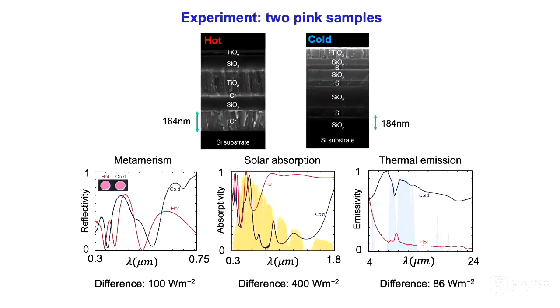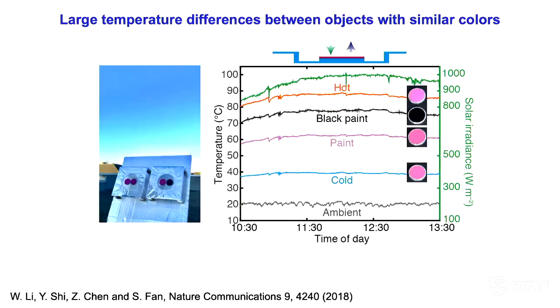He then did an experiment where he made two different structures that are both visibly almost the same. They both look pink, but they are designed based on the thermal load consideration, and he put them under the sunlight and measured their temperature. The remarkable result is that even though they look almost the same, the temperature difference between them is about 40 degrees Celsius. So you can get a huge temperature swing for things with the same color. And the commercial paint, which has a similar color, sits somewhere in between. This gave an indication that there is tremendous potential in keeping the visual appearance of something the same, but significantly affecting the thermal properties for either heating or cooling application.